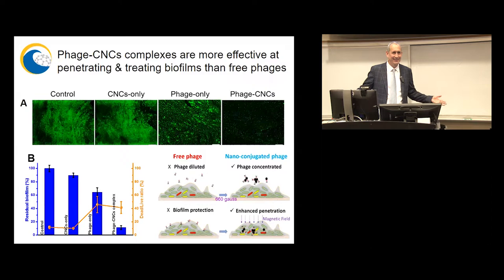It's just rust, essentially. So they're not going to be killing the bacteria, but you can push them in and pull them back out, and that disrupts the biofilm. These polyvalent phages do really well. I mean, if I use a normal phage, it won't do this well, because they not only have a broad host range, they also pack some depolymerase enzymes on them that break down part of the biofilm. But when I load them onto these nanoparticles and give them a little help penetrating with a weak magnetic field, they do much better. So this is very encouraging.